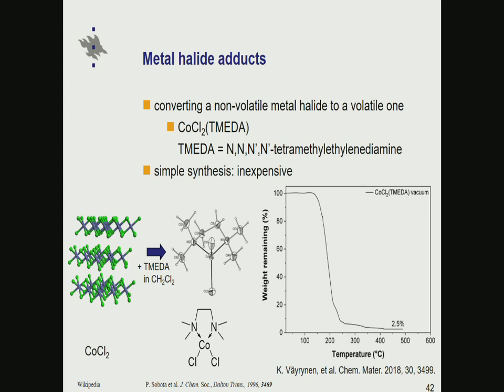Okay, then I already said that there are some metal halides which are not volatile at all. Quite recently, we went from these homoleptic metal chlorides to heteroleptic, so that we synthesized adducts of, in this case, cobalt chloride. We did the same also for nickel chloride. Cobalt dichloride is a 2-dimensional material, so it has infinitely long structures in the planes, and as a result, it's not volatile at all.